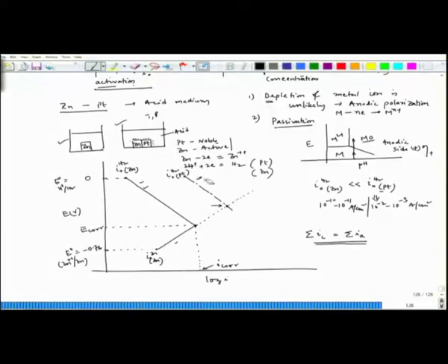Now, since it is a log scale, it will go at this point, because I have to add at every potential this one and this one, these two current densities, and get the new current density, which is this one. Similarly, here we have to add this point as well as this point to get the new current density, which is this point, the new IC.